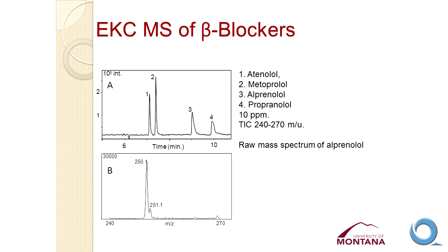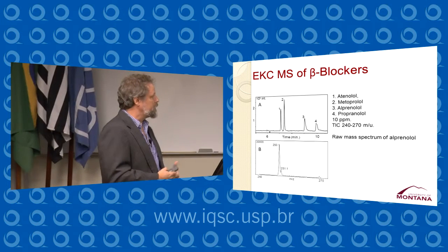Can we use these with mass spec detection? Yes, we can. This is EKC mass spec using electrospray ionization. We had 0.12% nanoparticle. This is a butyl acrylate acrylic acid nanoparticle in the background electrolyte. And we're separating four different common pharmaceutical compounds and detecting them by mass spectrometry. We're using a total ion chromatogram here between the range of 240 and 270, which is wide enough for these four compounds. If we look at any one of these compounds, in this case alprenolol, we can get a nice mass spectrum for that compound and identify that compound.